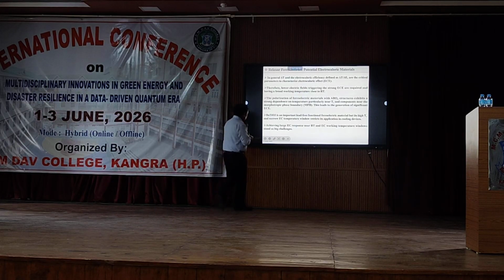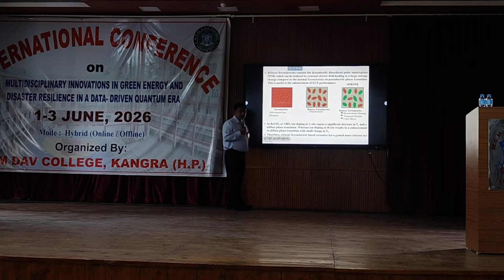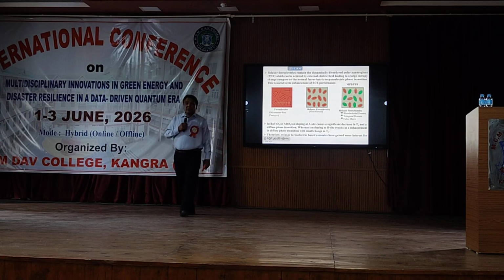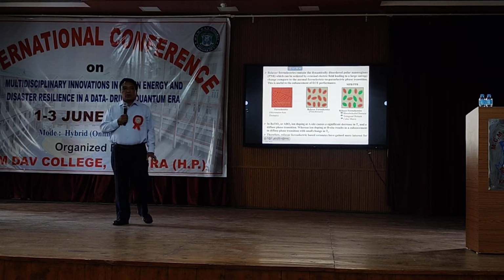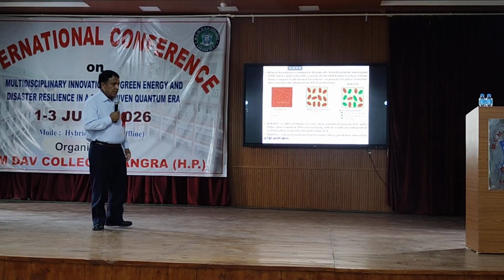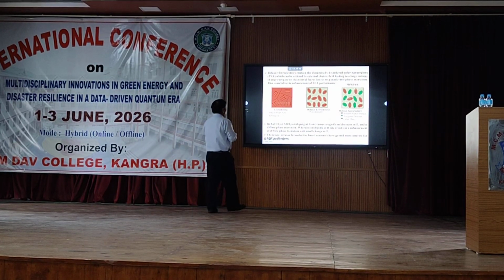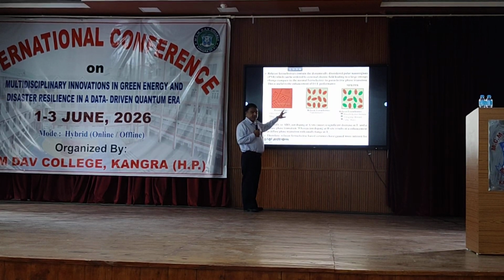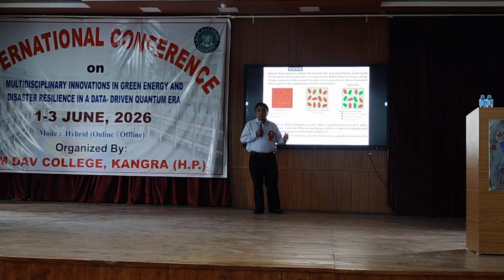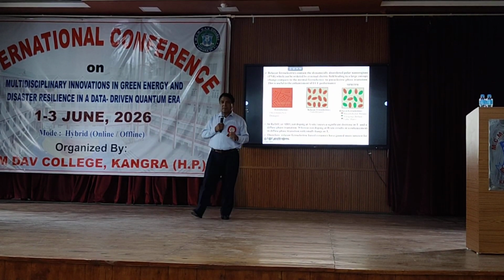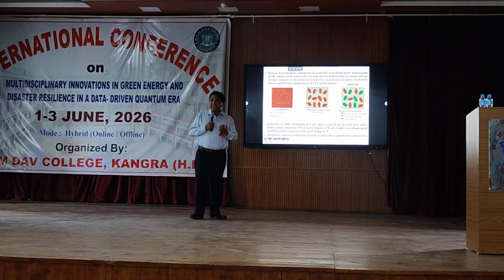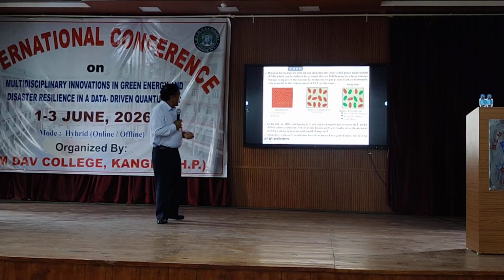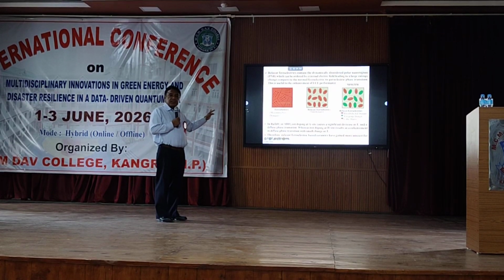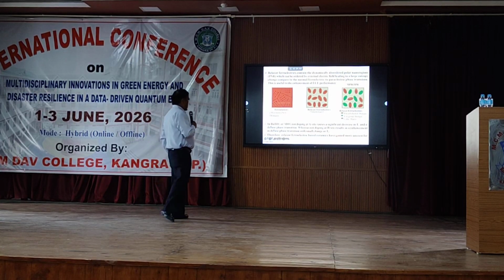So now come to the topic, this relaxor ferroelectric. The relaxor ferroelectric differ from the normal ferroelectric because of existence of nanopolar region. Because normal ferroelectric, one can see here the bigger domain size in micrometer size, but relaxor ferroelectric, there will be smaller domain size in the nano region, which helps to increase the temperature stability of the polarization. This is one factor that the relaxor ferroelectric is very promising to enhance the electrocaloric effect. Not only electrocaloric effect, we will see shortly, the energy storage also comes better from relaxor ferroelectric.